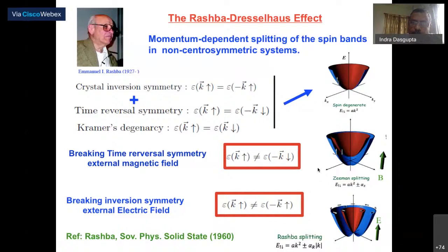Rashba spin orbit coupling essentially refers to momentum dependent splitting of spin polarized bands in non-centrosymmetric systems. So you have a system which has to break inversion symmetry. In a system, if you have crystal inversion symmetry and time reversal symmetry, then you have what is known as Kramers degeneracy. As a consequence, your up spin bands are completely degenerate with your down spin bands. For example, if you do a non-spin polarized DFT calculation, you precisely get this.